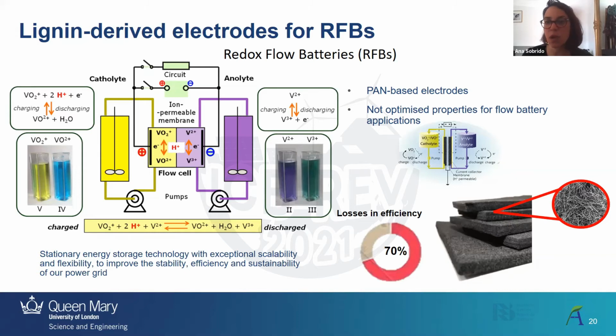The most popular redox flow battery is called the all-vanadium redox flow battery. It has vanadium species on the positive and negative sides. On the positive we have 4 and 5, and on the negative 2 and 3. So when you're charging, vanadium 3 reduces to vanadium 2, taking up one electron, whereas on the other side, the vanadium 4 oxidizes to 5, releasing that electron. And then in the discharge process, the opposite happens. So that's the redox flow battery working principle.